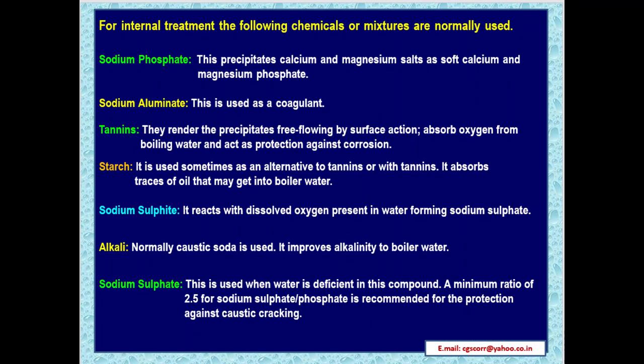For internal treatment, the following chemicals or mixtures are normally used. Sodium phosphate: this precipitates calcium and magnesium salts as soft calcium and magnesium phosphate. Sodium aluminate: this is used as a coagulant. Tannins: they render the precipitates free flowing by surface action, absorb oxygen from boiling water, and act as protection against corrosion. Starch: it is used sometimes as an alternative to tannins, or with tannins; it absorbs traces of oil that may get into boiler water.